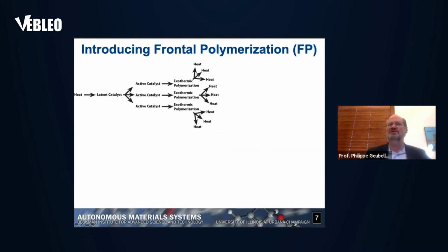So the approach that we've adopted is based on the concept of frontal polymerization. To schematically illustrate what it is, the idea is to put a latent catalyst in a monomer to introduce a thermal trigger that activates the catalyst and starts a chemical reaction. It's an exothermic polymerization, and therefore the heat of reaction polymerizes the material, but also heats up the material ahead of it, activating the catalyst, and eventually the thing propagates as a wave, right?